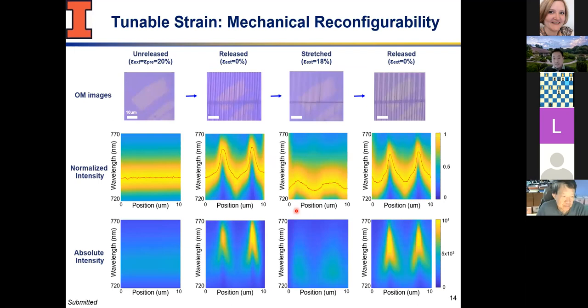Before I go into the drift business, what we thought was interesting from this mechanical system is that things are reconfigurable. Here I want to show you, you start from a flat flake that was homogeneous everywhere in terms of emission, about 740-ish, let's say. But once you create a wrinkle, you start to split the energy between closer to 740 and then 750 or smaller energy. And as you stretch again close to that initial flatness, you make them much more homogeneous. And then you can create this pattern of energy split again.